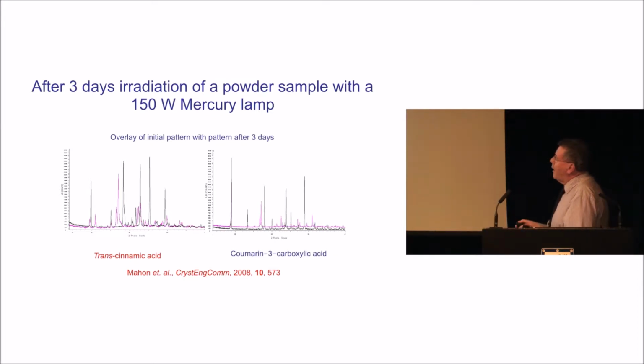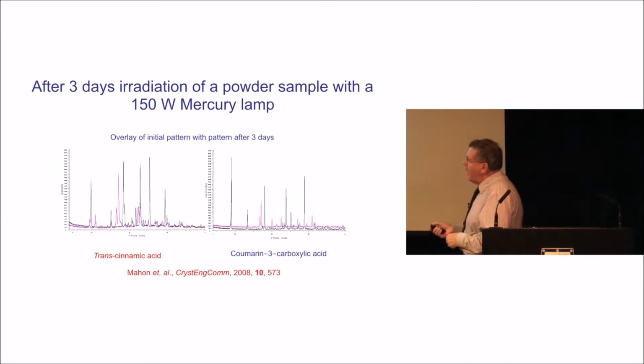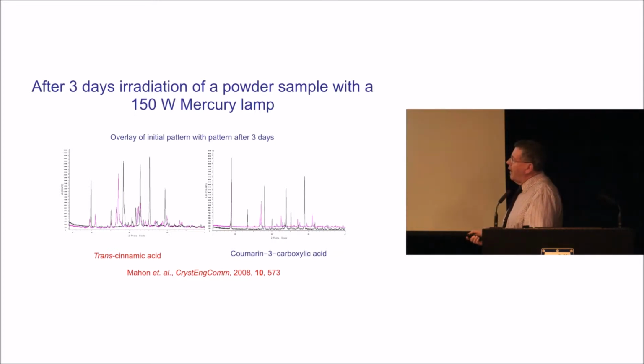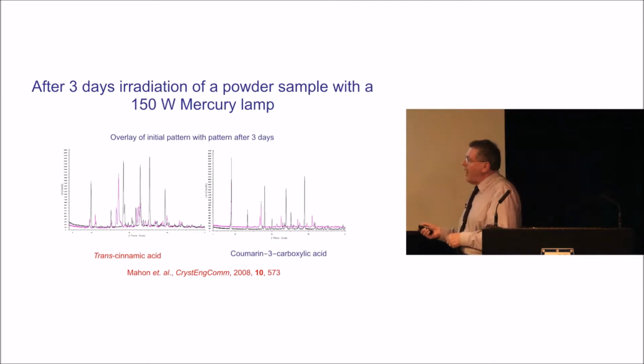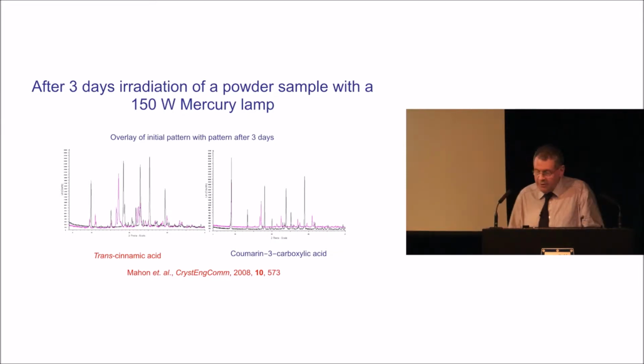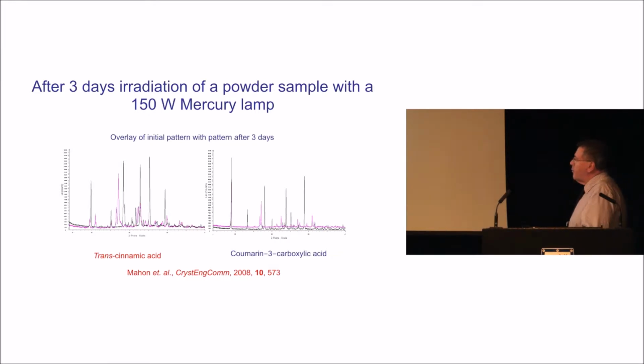And to prove that they did, we have powder patterns, and you can see for the cinnamic acid and the coumarin, the changes in the powder pattern at the end of 3 days, where the black is the original monomer form, and we have the change to the cycloaddition product.